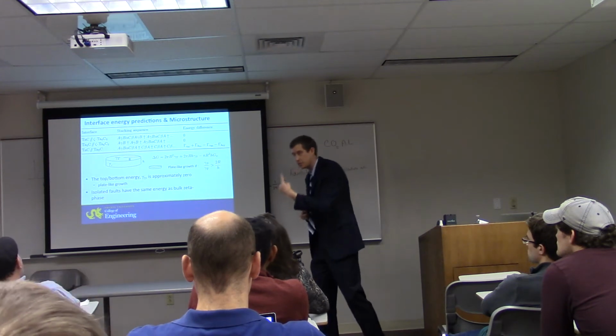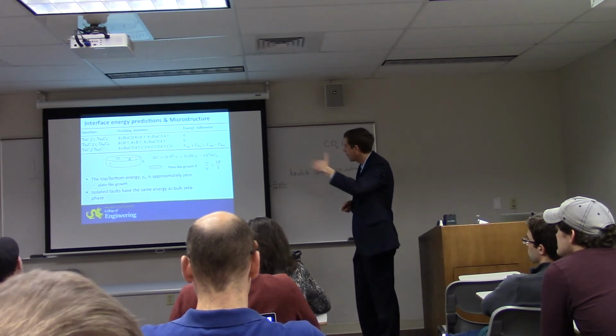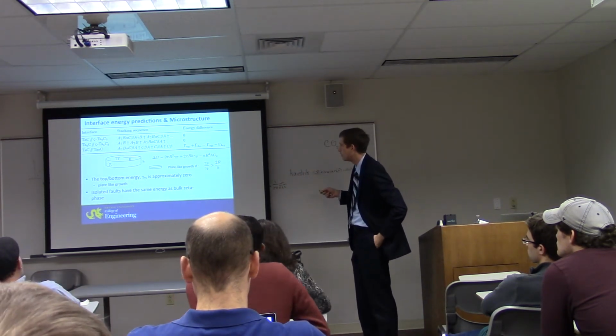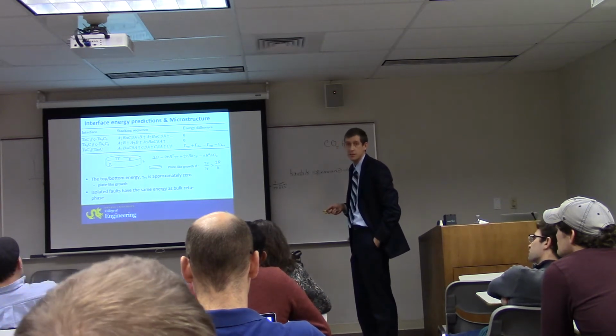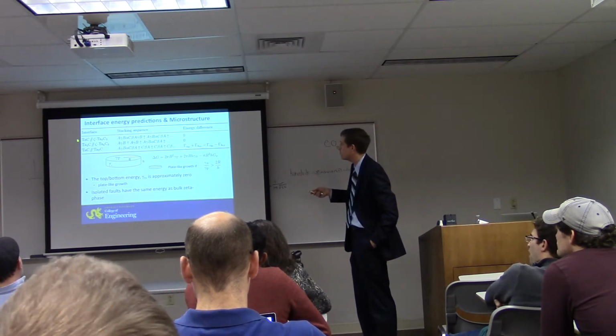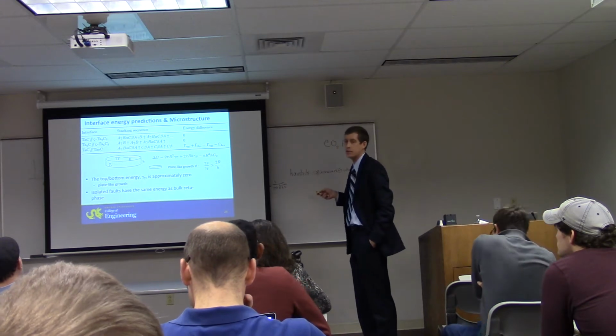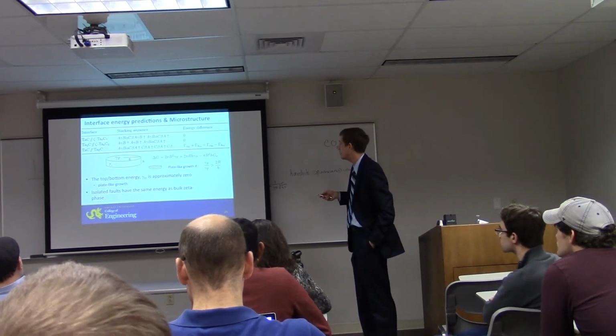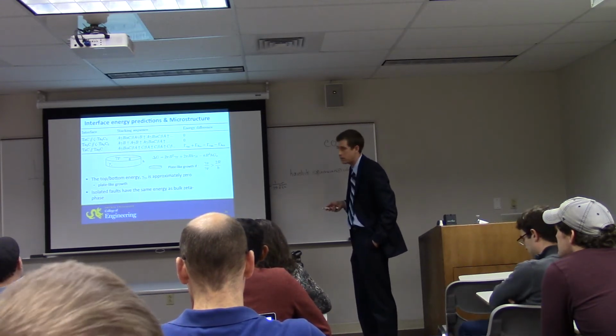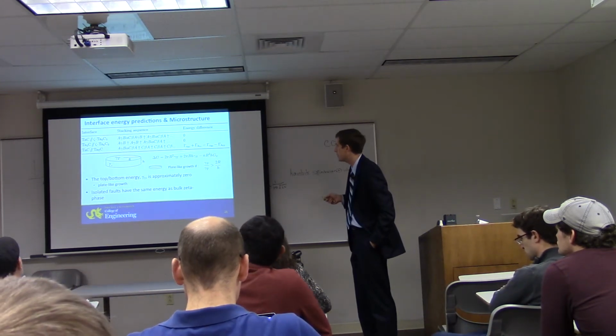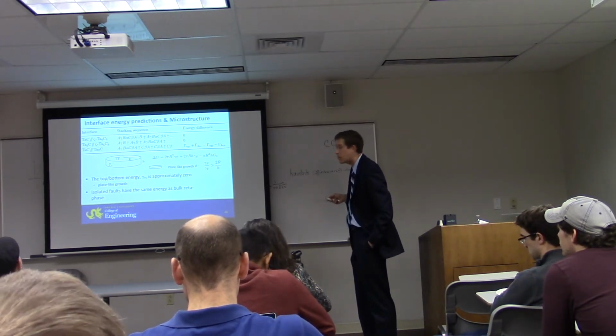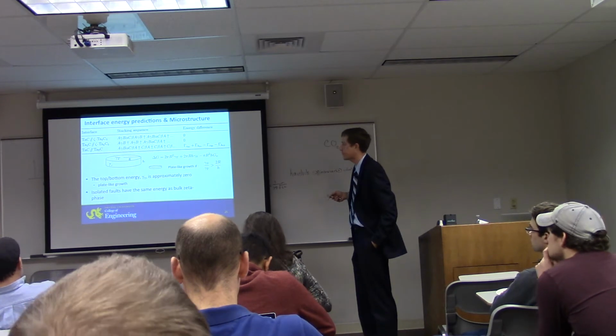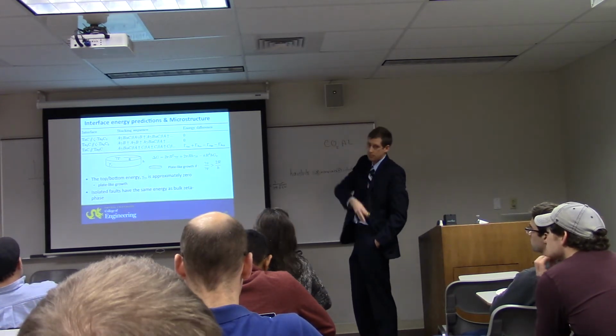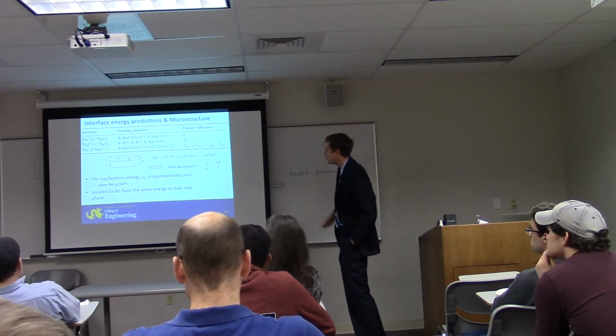The first thing I said was that there's no interfacial energy. So we can now take our model and compute the interfacial energies using the stacking sequence. Between TaC and the zeta phase, we get identically zero in the model. Ta2C and the zeta phase, we get identically zero. And between TaC and Ta2C, this is actually a negative number, because locally it has formed a piece of zeta phase, which is more energetically favorable than either of these two.